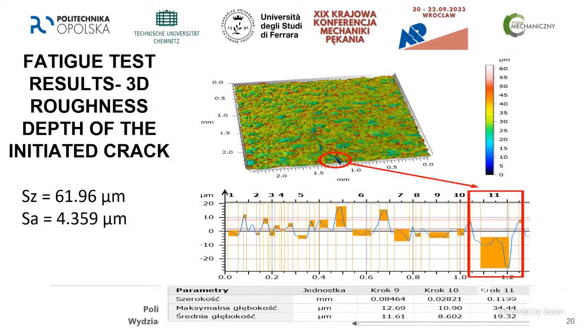Beside this, we have made a lot of tests in terms of scanning surface, 3D surface roughness, 2D surface roughness, and so on. One of the elements I would like to show you is the fatigue test results for the 3D roughness depth of the initiation crack, right? It's in Polish because at first I didn't know if I should prepare everything in English. Some of the diagrams also have elements in Polish because of Polish software, but the maximal depth for the crack that we had was 34 micrometers for this analyzed specimen.